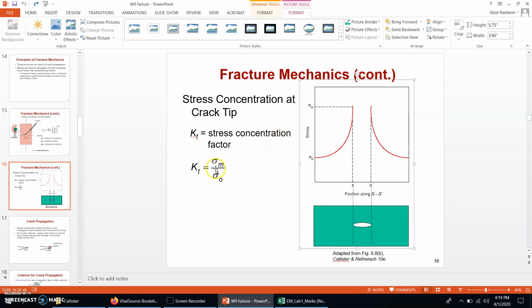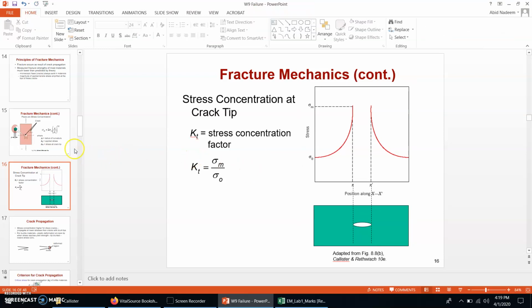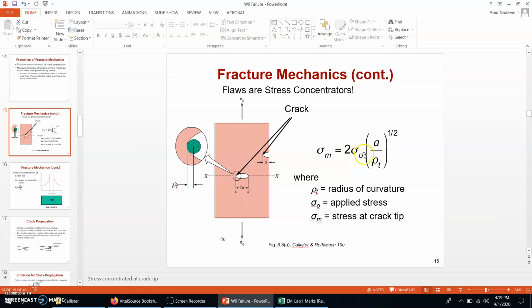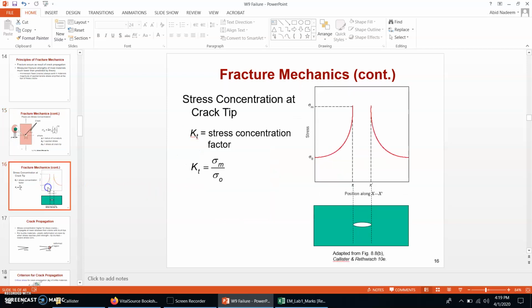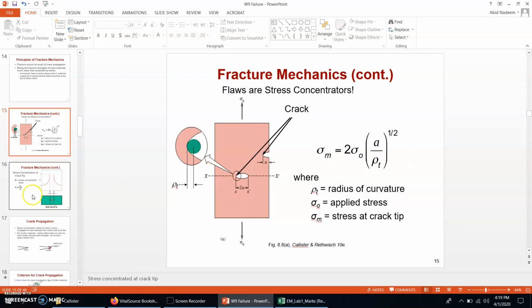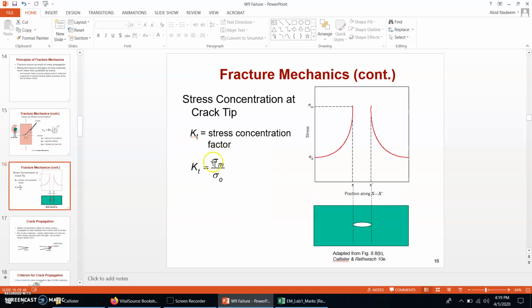In this way we can take a ratio of sigma m and sigma naught, and that ratio is called the stress concentration factor. So the stress concentration factor is basically the ratio of sigma m and sigma naught. As we can see over here, if you take sigma naught from this side of the equation to here, the remaining value is 2 times the bracket a over rho t to the power 1 by 2. That is the ratio sigma m over sigma naught, which we define as the stress concentration factor.